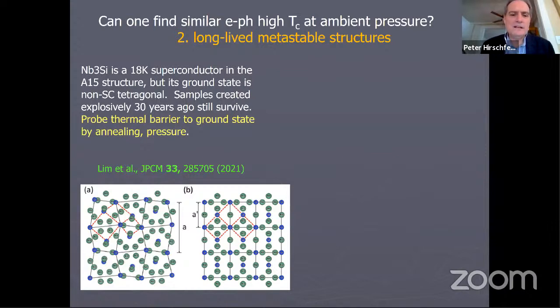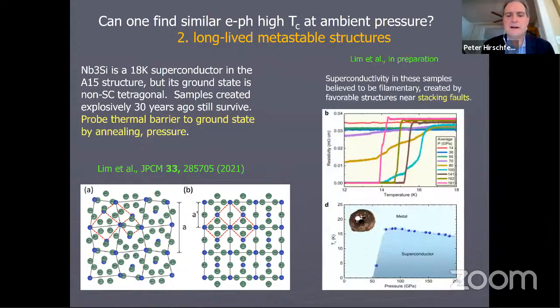And what we did in our group, Greg Stewart, one of my colleagues, had this sample in its drawer. It had been sitting there for 30 years since it was made, and it was still superconducting at the same TC. And what we did was heat it up above room temperature and try to probe the thermal barrier to see if we could estimate the barrier height.